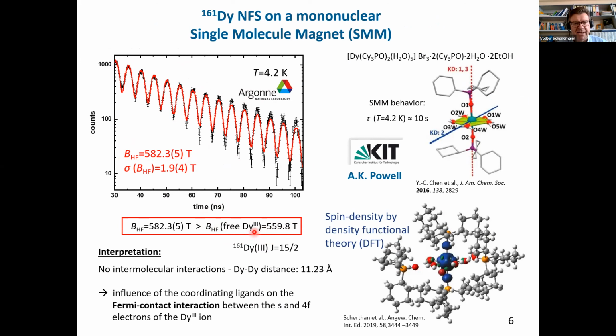So the reason seems to be, or is definitely, a molecular one. Actually, one thought about 4f magnetism as a very localized magnetism. But in this complex, there is spin density not only on the dysprosium, but also on the ligands in axial direction. And this influence of the coordinating ligands on the Fermi contact interaction between the s and the 4f electrons causes this relatively high hyperfine field.